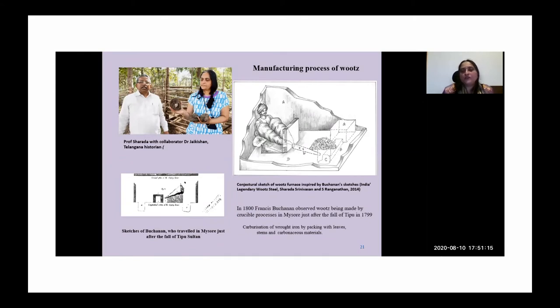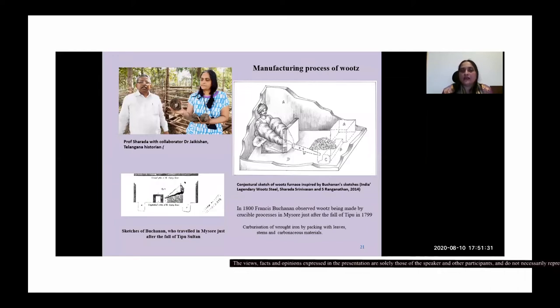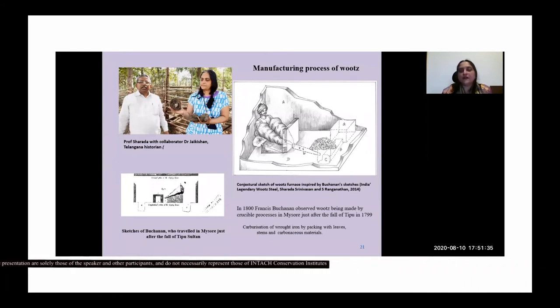And what the wootz process really entailed was that wrought iron was placed in these little crucibles and fired at these high firing temperatures under very highly reducing conditions, so that the iron got carburized and the carbon got into the iron to give this composition of high carbon steel.